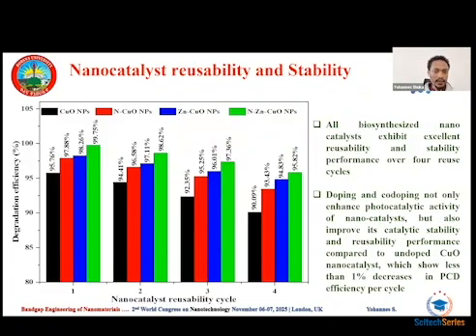Finally, we examined the reusability and stability properties of these nanocatalysts. As you see here, we observe maximum degradation, and we observe maximum reusability and stability for all materials, but the codoped material showed excellent reusability and stability compared with the pure and the nitrogen or zinc doped copper oxides.